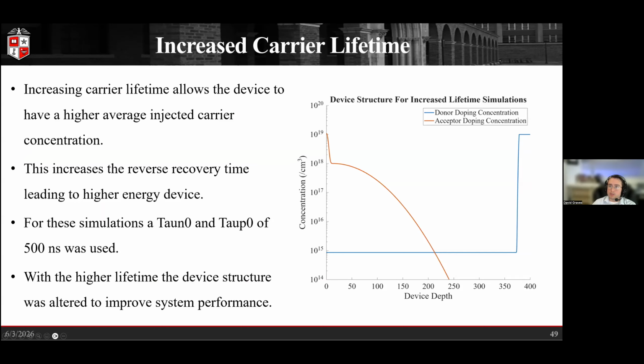And so one of the things that we continue to iterate on with this is different structures based on increased carrier lifetime. If we're not directly bound by the carrier lifetime from our characterized device, we're able to increase that to higher amounts, right? As we mentioned earlier, we were using 50 nanoseconds. We can increase that to 500 nanoseconds, which is still reasonable for silicon carbide.